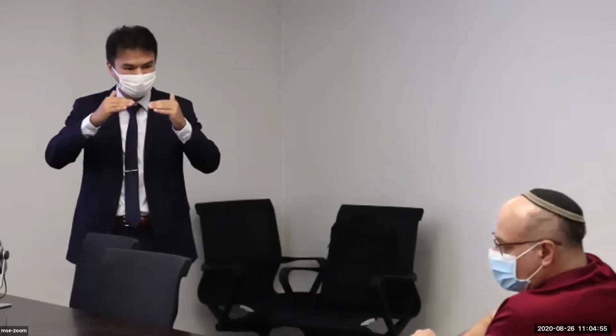You can have a lot of strategies to do that. Someone can use thermal annealing, use different solvents, or even additives, right? You can control the crystallization of the individual phase to achieve the final optimized morphology. But as I also showed, your optimized morphology for performance may not be the optimized morphology for stability. So this is striking a balance, right? How you can simultaneously achieve both of them.